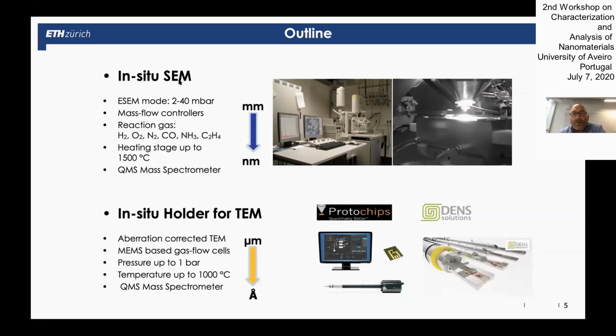They can operate in a mode where you can actually introduce gases into the chamber. And yeah, I have here written down the pressure regime. In fact, you can, with some modifications of the vacuum system, operate them basically from the base pressure, which is like 10 to the minus 5 Pascal, all the way up to 1 bar, that's 10 to the plus 5 Pascal. So it's nearly 10 orders of magnitude in pressure. That's quite huge.